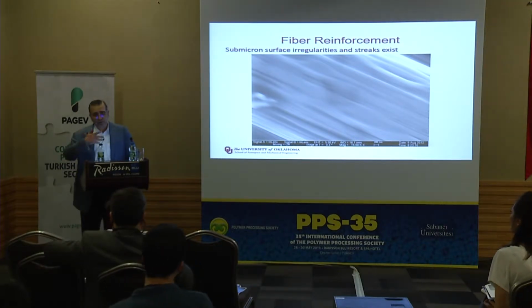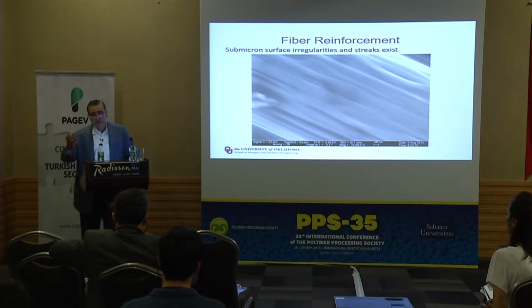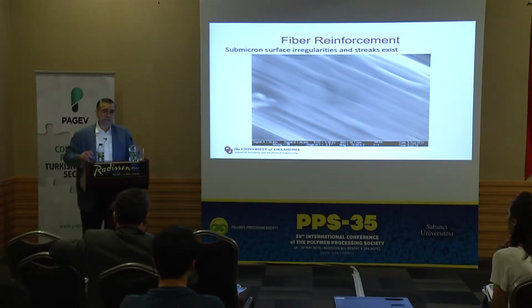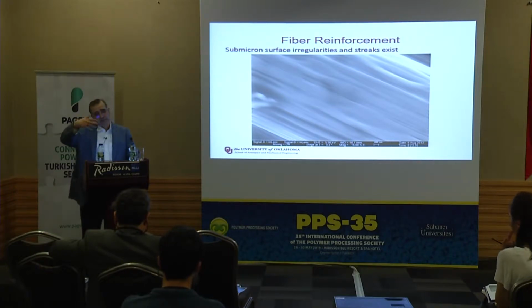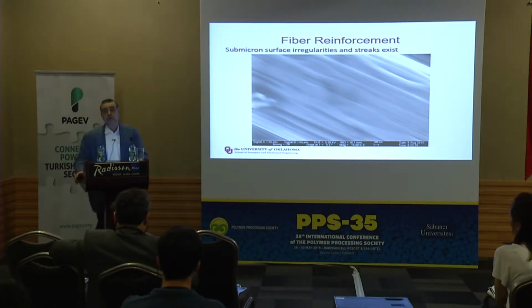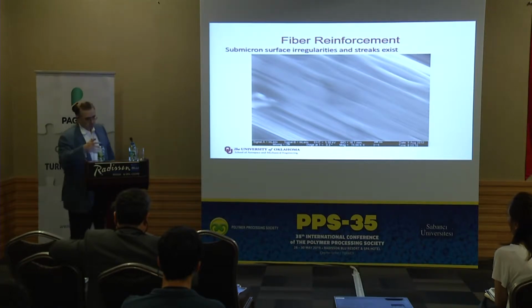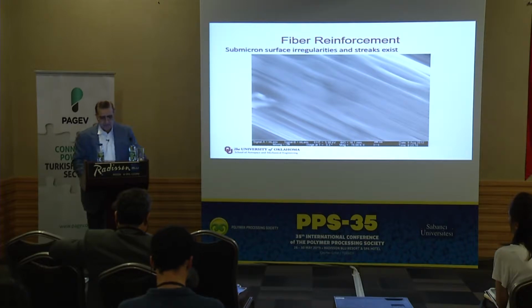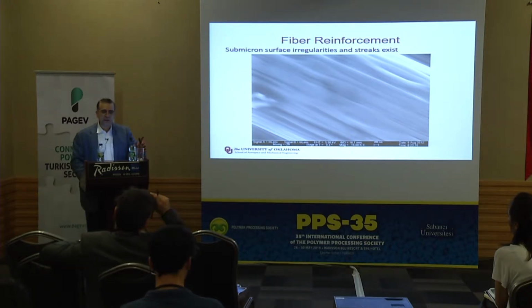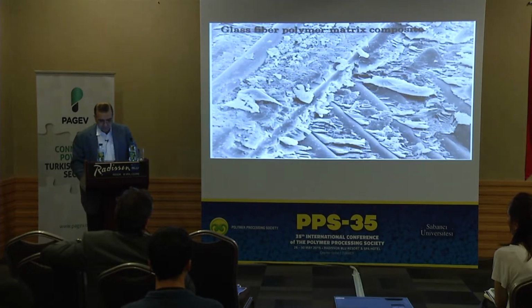If you heat carbon fibers or glass fibers to 400-500 degrees C, you will essentially desize the fabric, and you can apply your own sizing. And if you are in polymer chemistry and surface chemistry, there's a whole group of people dealing with the surface chemistry of fibers and the sizing formulations. And that's very important in the interfacial properties, okay? Because that's how your stress or the load is transferred from within the composite, between the fiber and the resin.